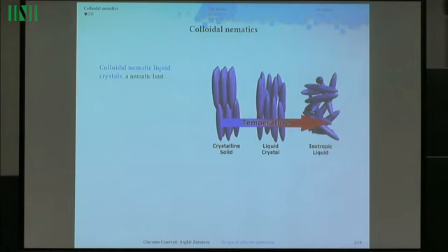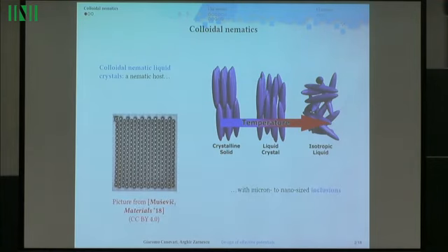And what we do is that we put some inclusions, some particles into them. Many small particles, small meaning perhaps micron size or less, so actually very large compared to the molecular length scale, but still small compared to the size of the domain. And the result is the colloidal nematic. So that's a composite material. And the interest in these colloidal nematics is that the properties of this composite material may be even quite different compared with the properties of the nematic liquid crystal host alone.